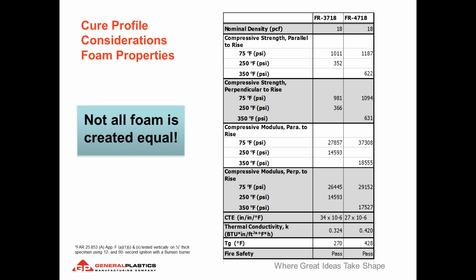So even though they're both 18-pound per cubic foot thermoset cellular plastics, the formulations are quite different. And the 4718 is an epoxy hybrid material that allows these higher glass transition temperatures and higher strengths. So as we move down through the tech data sheet, you'll see on the CTE, there's also a difference there as well. The lower CTE just helps reduce the amount of thermal compensation you need. Now, as the CTE is measured, that CTE that we report on our data sheets is from room temperature up to about 30 or 40 degrees below its glass transition temperature.